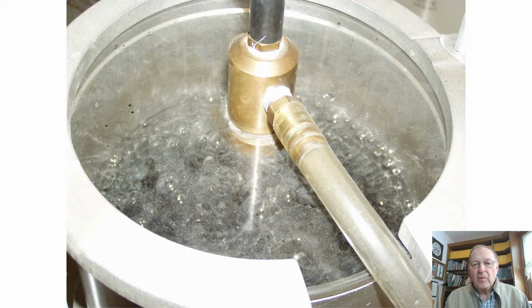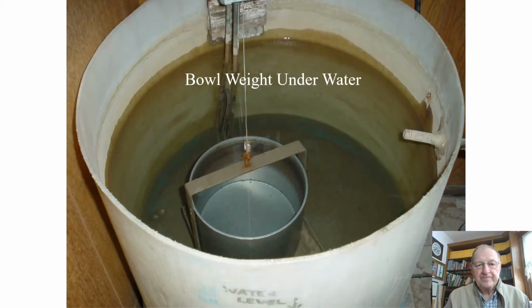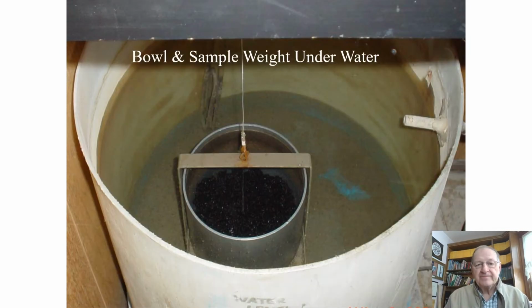Here you can see what it looks like while it's under vacuum, and you can see that the water is bubbling. It's almost like the water is boiling. There's air that's coming out of the sample. Now, before we would have used the bowl, we would have determined what the tare weight of this bowl is underwater, with no sample in it, of course. Now, after this vacuum saturation, we weigh the bowl and the sample underwater.